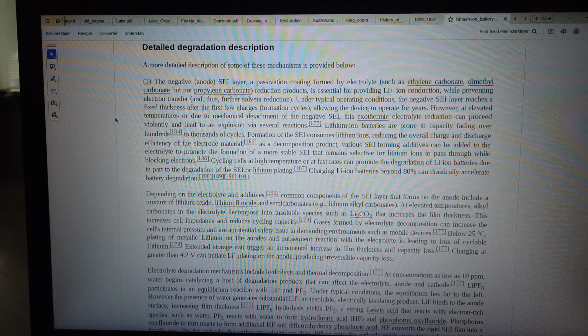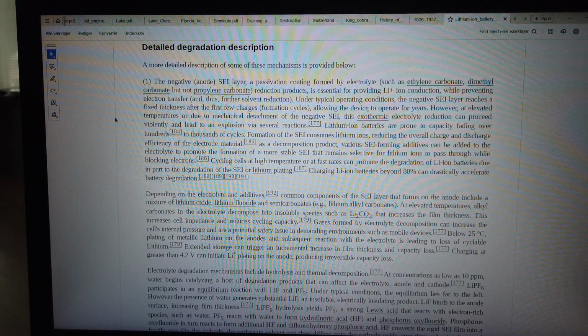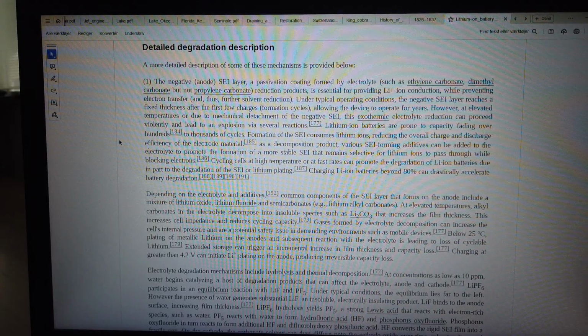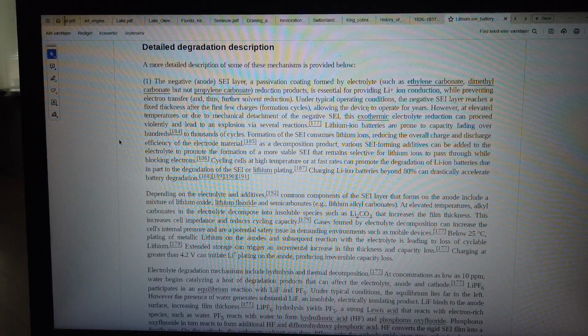However, at elevated temperatures or due to mechanical detachment of the negative SEI, this exothermic electrolyte reduction can proceed violently and lead to an explosion via several reactions. Lithium-ion batteries are prone to capacity fading over hundreds to thousands of cycles. Formation of the SEI consumes lithium ions, reducing the overall charge and discharge efficiency of the electrode material.